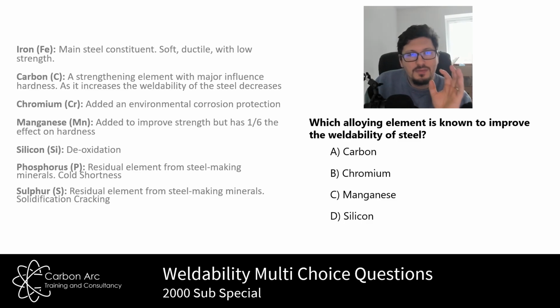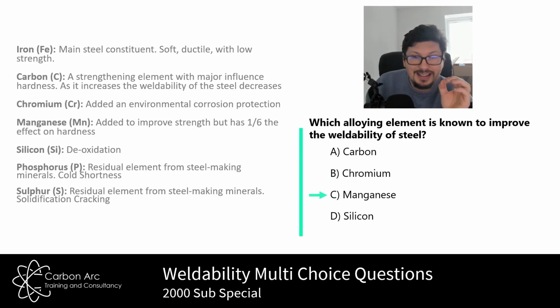Okay, here we've got one which is, which alloying element is known to improve the weldability of steels? Now, weldability is the ability not to crack, so we want to reduce the amount of carbon in our system as much as possible, and we do that by using manganese. So with carbon and manganese in your system, you can get more strength but reduce the effect of hardness on our process.